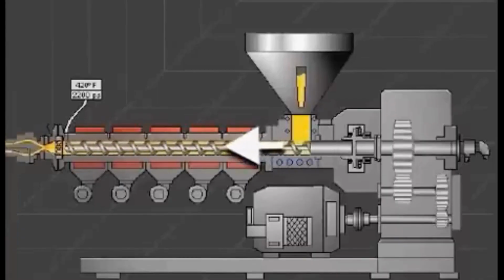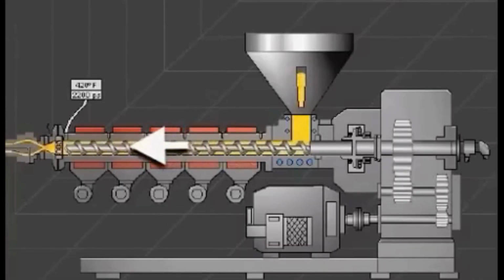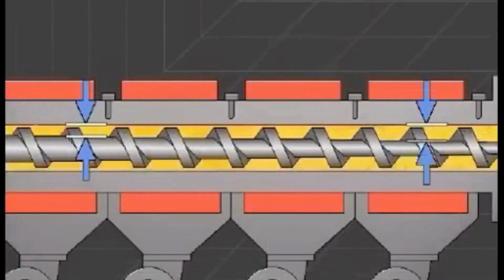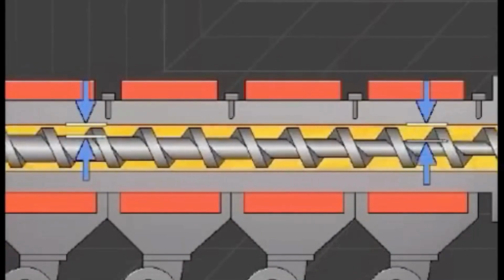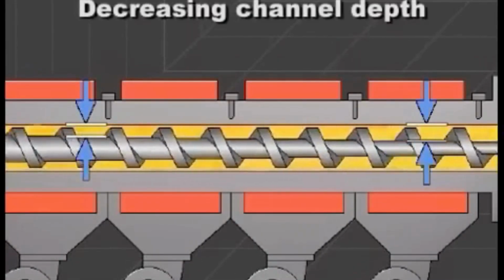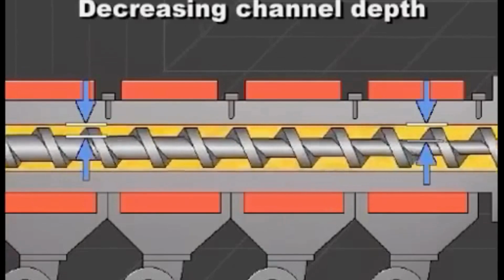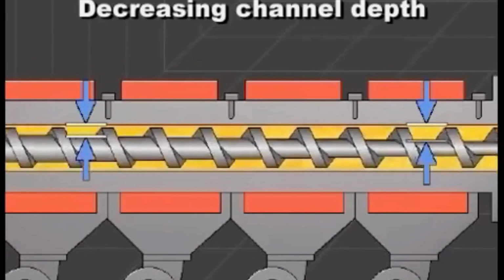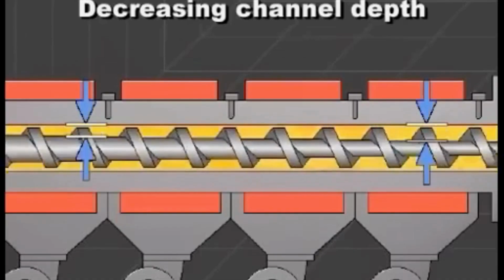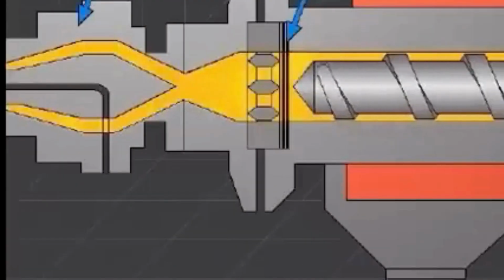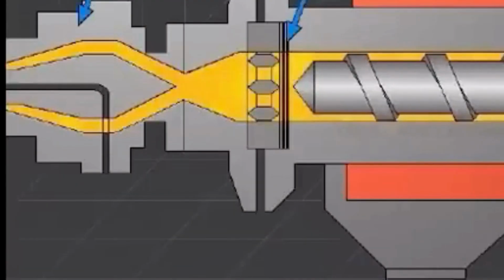After grinding, the regrind chips are blended with our selected ratio of virgin or post-consumer PET, depending on the production requirements. This blended material is metered into the extruder's feed throat, where the process of converting solid PET into new sheet begins. Inside the extruder, the chips are conveyed by the screw through a series of temperature-controlled zones.